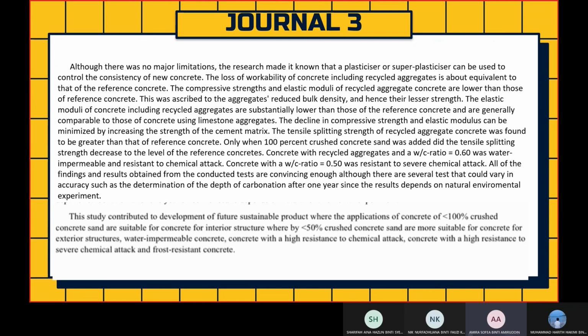All of the findings and results obtained from the conducted test are convincing enough, although there are several tests that could vary in accuracy, such as the determination of the depth of carbonation after 1 year, since the results depends on natural environmental experiment. The study contributed to the development of future sustainable product with the application of concrete below 100% crushed concrete sand are suitable for concrete for interior structure, whereby 50% lower crushed concrete sand are more suitable for concrete for exterior structures, water impermeable concrete, concrete with high resistance to chemical attack, concrete with a high resistance to severe chemical attack, and frost resistant concrete.